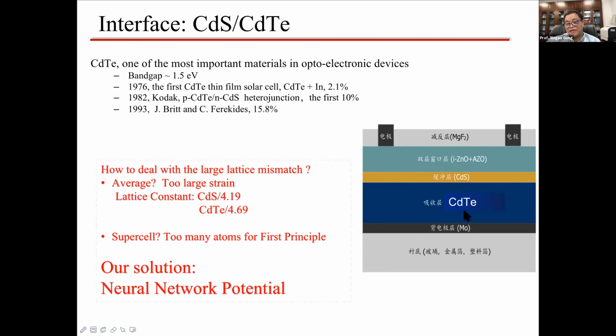For instance, look at this system, cadmium telluride. It is one of the most important materials in optoelectronic devices. The band gap is something like 1.5 electron volts, one of the best band gaps for the solar absorber, which was known in the 1970s. At that time, people were trying to use it for the solar cell, and up to the 90s they reached 16%. Now it is something more than 20%. It is one of the best thin film solar cells, but from the computational side, how can we understand it?